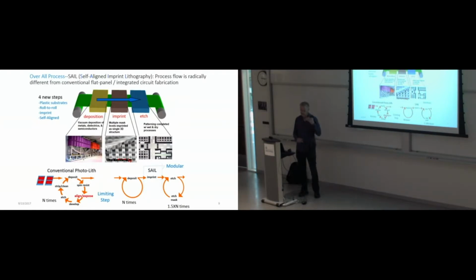So normally photolithography is a 0-1 operation. If there's no photoresist, you etch. If there is photoresist, you don't etch. Well, this we actually can have different levels, and using those levels, we can have all the layer information imprinted in one step, and then we do the etching all in one step.